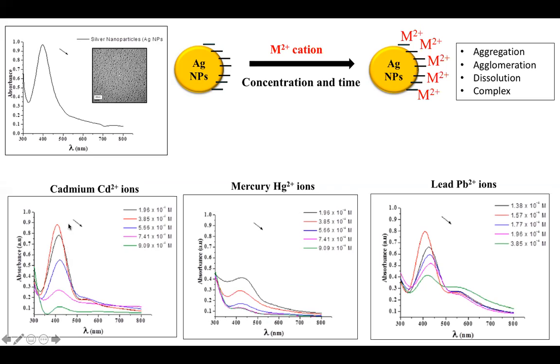As you can see, in the presence of each one of them, there's a slight red shift toward the right, or higher wavelengths, which indicates that some aggregation is taking place. Even with cadmium, there's starting to be a quenching, a decrease in that peak, and broadening. That broadening of the peak indicates that we're starting to see some aggregation of these nanoparticles. In the case of mercury, there's a huge dissolution of these nanoparticles, as the peak is almost completely quenched immediately at all concentrations and broadened out. So again, it tells us there's a change in the stability of these nanoparticles at different concentrations over time.